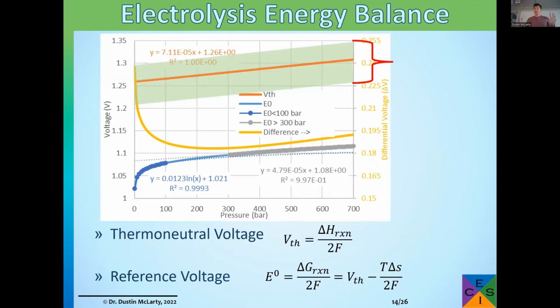So that brings me a little bit to the electrolysis itself and the thermodynamics happening in the water splitting reaction when we go to pressure. We have some benefits, but actually a few drawbacks from a basic fundamental thermodynamics of going to pressure. The orange line here is the thermoneutral voltage. This is the voltage you could operate your water splitting where you wouldn't be heating up or cooling off your stack. So it's a really good operating condition because you don't need balance of plant doing any cooling or supplemental heating of your stack itself.